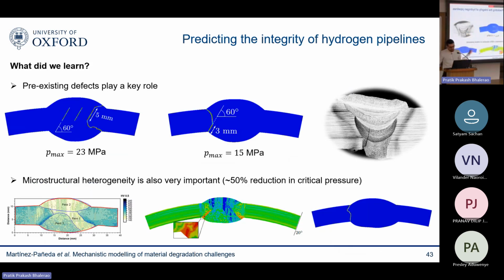And of course, what we found, among other things, is that pre-existing defects play a big role, as you would imagine. So we tried to do a systematic characterization of those pre-existing defects, and Tushar found that if you align a 3 millimeter crack along the heat-affected zone, the critical pressure at which your pipeline will fail is 15 megapascals. And that's problematic because this is one of the pressures they're considering for hydrogen transport, and they know they have defects like this, they know from pipelines taken out of service that they have defects like this